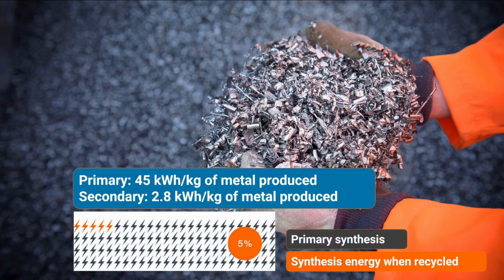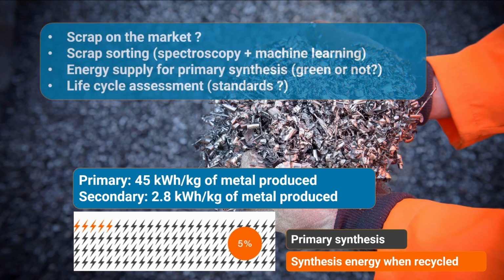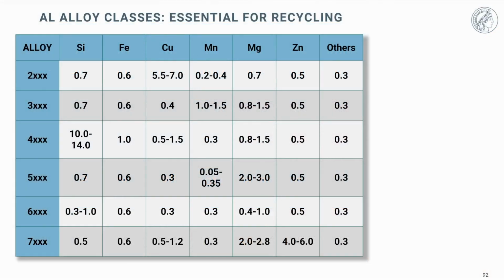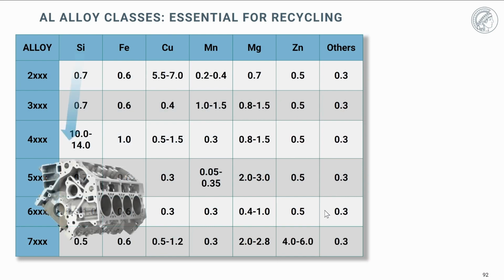Now a few words also about aluminium. I already mentioned before that there's a very high discrepancy between the primary energy you need to make aluminum from the ore and the very low energy that you need when you make it from scrap due to the low melting point of aluminum. And this amounts to only 5% of the energy compared to the primary synthesis. However, aluminum alloys cannot be mixed very well.